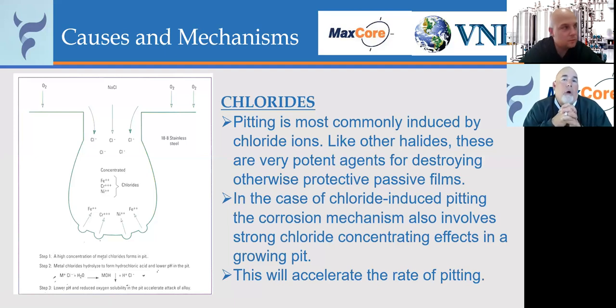Now, again, it depends on the material itself, because as material starts to form and solidify, what happens is you have all these alloying elements that go into homogenization. And you don't have the same corrosion resistance across the entire surface of that steel. So you're going to have some areas that may be a little bit stronger than other areas. So it depends on how it actually forms. So pits can be generated from where the passive layer has been damaged just due to a simple thing as a scratch on the surface of the steel, where somebody has gotten in and walked on it and scratched it and damaged that passive layer, dropping a wrench or a screwdriver down inside of a tank, or even an inclusion from the mill of some type of tramp element that doesn't have the same type of corrosion resistance. So there's all types of things that come into play that you have to look at.